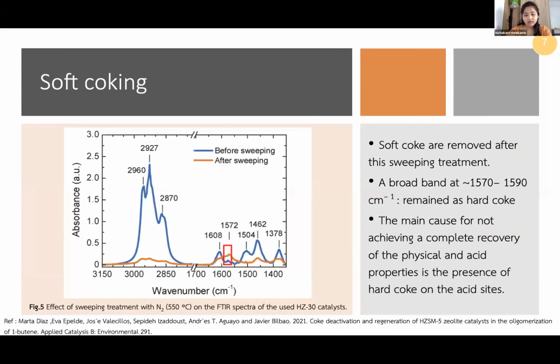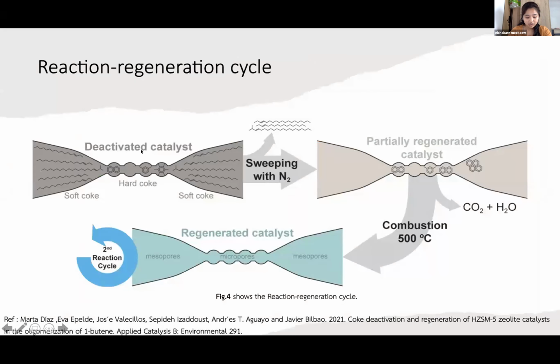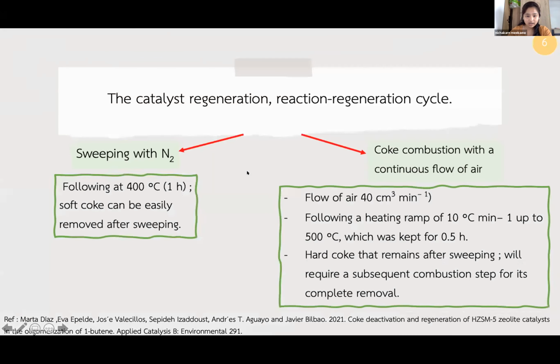Sweeping with nitrogen at 400 degrees Celsius for 1 hour, and the second, coke combustion with a continuous flow of air, following a heating ramp of 10 degrees Celsius per minute up to 500 degrees Celsius for half an hour.